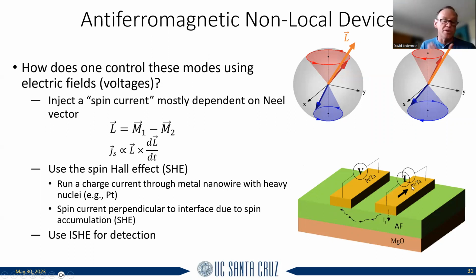Remember, the spin Hall effect doesn't require anything magnetic. It just has to have relatively strong spin orbit coupling. This creates a spin current going downwards, which creates excitations in the antiferromagnet. The excitations travel to the left, and then the inverse spin Hall effect, when these are precessing right at the interface, creates a voltage that you can detect in the opposite way. So this would be a completely spintronic type device, because the information is carried through an antiferromagnet, which ideally is completely insulating. So there's no charge current going from here to here. You're running a current here, detecting a voltage here.